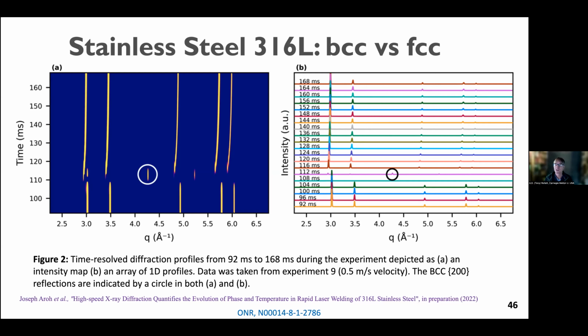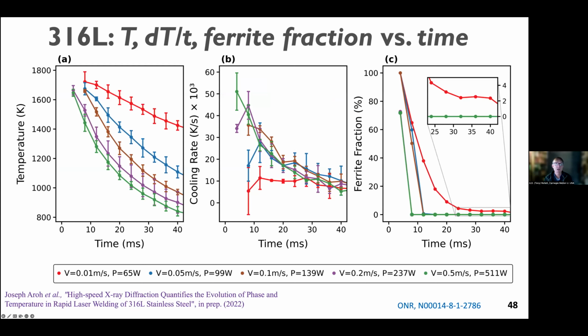And the unexpected thing was that this composition is supposed to be strictly FCC, but it turned out that for this particular experiment, when we looked carefully, we could find a frame in which it was very clear that the only phase present was actually the ferritic phase, the BCC phase. Not totally unexpected from the phase relationships, but really quite exciting to capture it, you know, in flagrante delicto, as you might say. And so we went on from that to say, okay, since we can actually see it and measure it, then we can do this as a function of the solidification conditions.